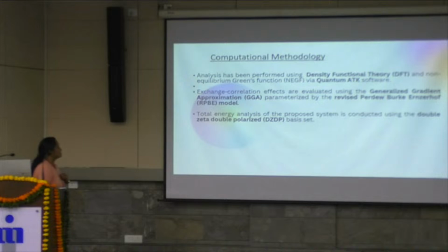The computational methodology includes density functional theory and the non-equilibrium Green's function using Quantum ATK. Using density functional theory, we optimized the structure having a graphene sheet with a water molecule, as well as the different contaminants of the radioactive elements. Then we checked the electronic properties as well as the transport properties, and we found some changes. As the exchange correlation functional, we used the generalized gradient approximation with the revised PBE model. Other parameters like a double zeta double polarized basis set were used. Different k-point meshes were checked before going for the optimization.